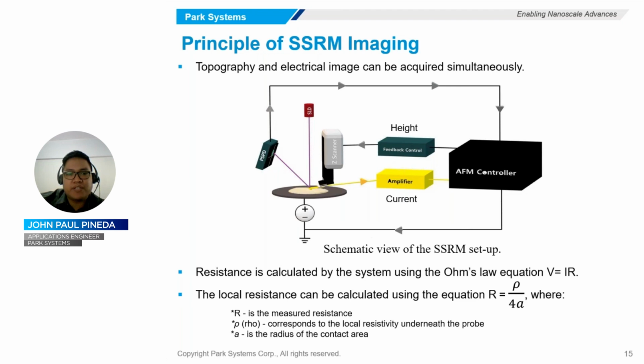Also, the measured changes are compensated by the AFM's feedback control, which maintains the cantilever's constant deflection by controlling the Z scanner movement. For SSRM imaging, if you are familiar with conductive AFM, the operation is almost the same. Both techniques use a conductive probe and operate in the contact mode regime.